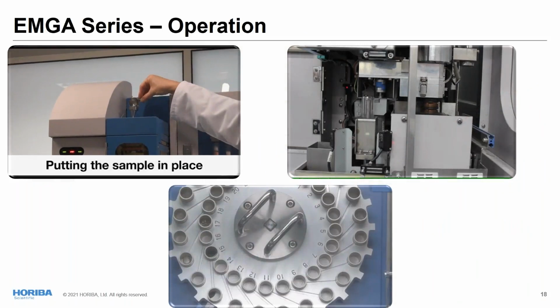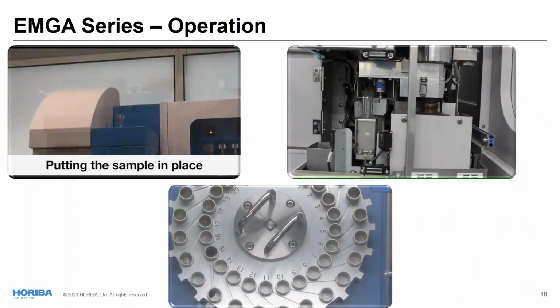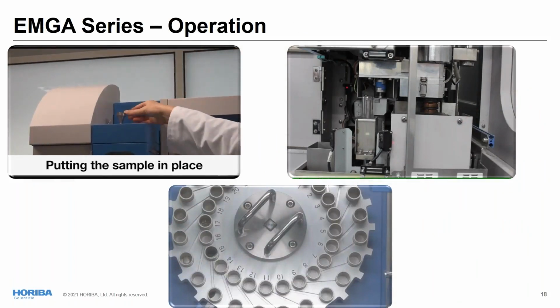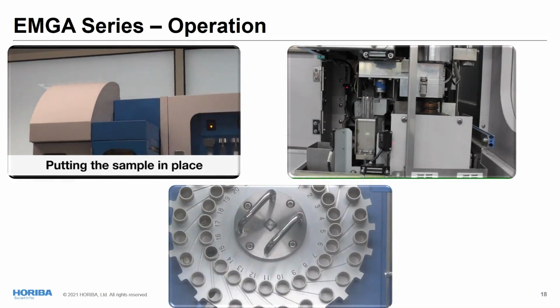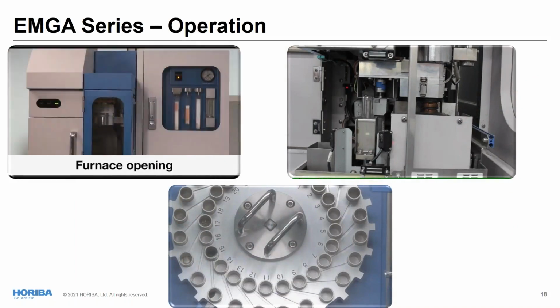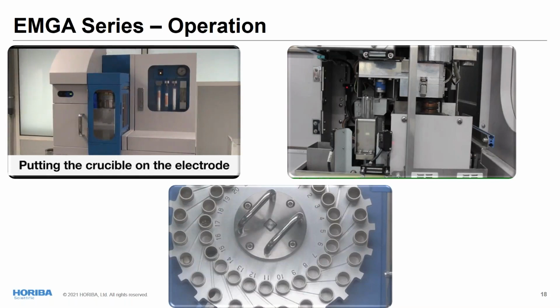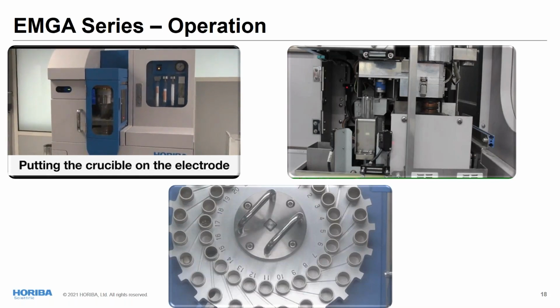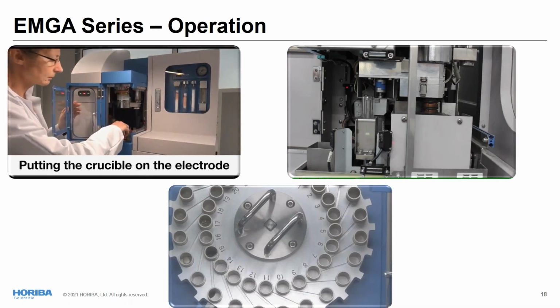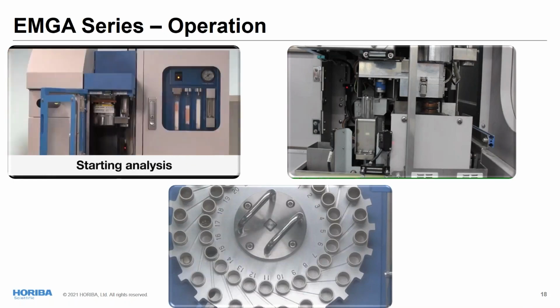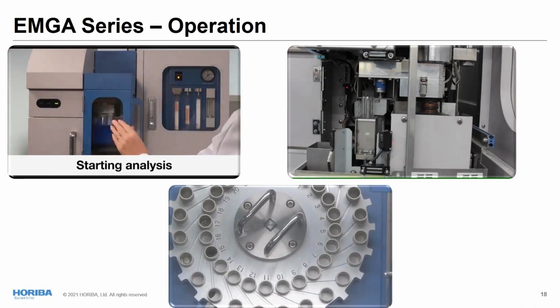Now you can see how it works here. You are introducing the sample on top in the dual loading system. You may use the funnel that is supplied for that. Once the sample is ready to be introduced into the crucible, you can open the furnace, place the crucible on the lower electrode, and from there you can start the analysis. By just pushing the button here, the analysis will start, the furnace will close, and the outgassing steps will begin, and the sample will be introduced when needed for the analysis.